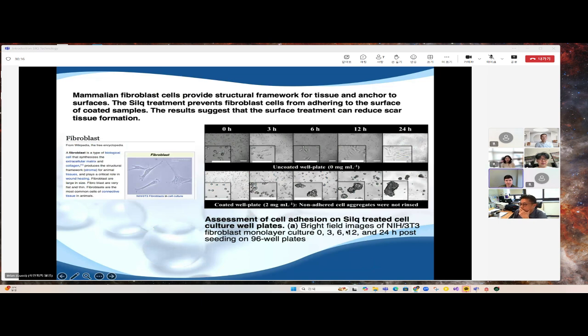This is a little bit more complicated, but I'll go through it slowly. So we tested fibroblast cells. These cells, this is from Wikipedia, create the scar tissue and collagen in our bodies. And when these cells adhere to surfaces, they form these long anchored structures shown here in the picture. You can see that same thing happening. They're circular cells, but after 24 hours, you can see here with the uncoated substrate, those cells forming these elongated structures, just like this.